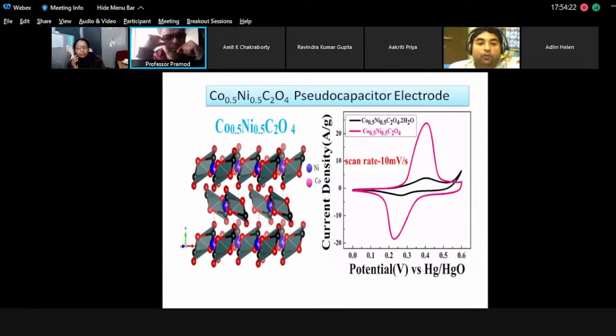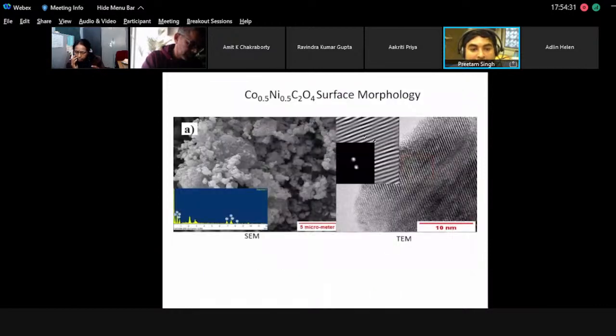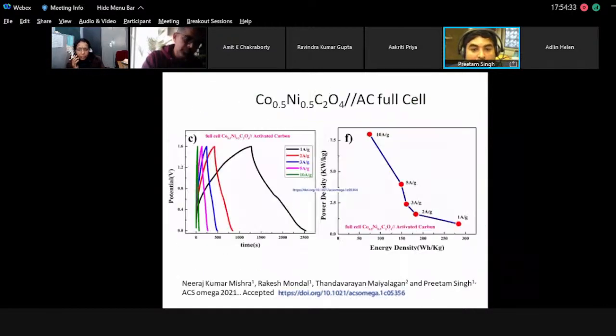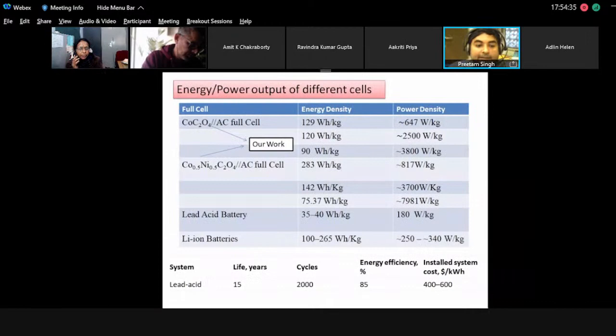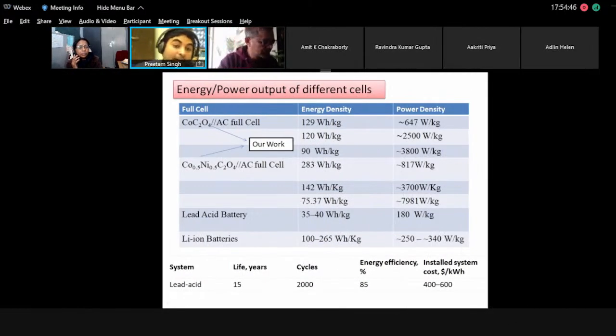Sir, in the same way we have developed other structures, and what we are working on in these frameworks, our exploration in that area also resulted in cobalt and nickel oxalate mixed structure materials. And now we are going to show you the final results, where we are standing. So these framework materials are generating a power density of 647 watt per kg, along with an energy density of 129 watt hour per kg, and these are many fold higher than the lead acid batteries' energy density and power density.